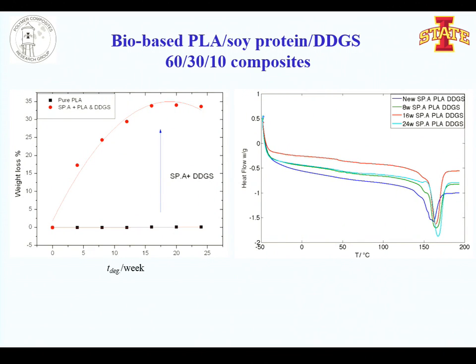A high concentration of soya protein in the blend makes the material not good mechanically. It can absorb a lot of water, very high water sensitivity. But adding a lot of DDGs makes the material more brittle. So we try to compromise the properties by adding the three components, PLA, soya protein, and DDGs, and decreasing the concentration of the soya protein a little bit. And we have found that the degradation is still very high for the blend, but nothing changes for the pure PLA. We cannot see any glass transition temperature once we add the soya protein, and the crystallization is a little bit increased, but the behavior is still the same.